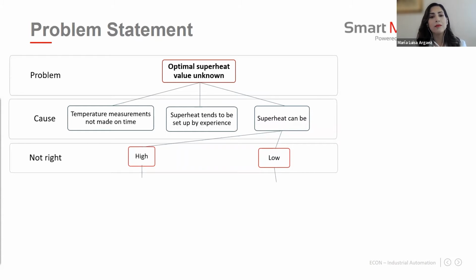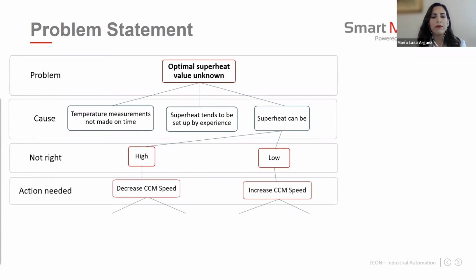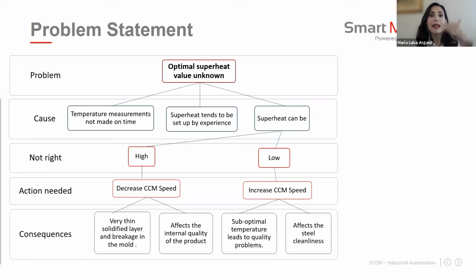Therefore, not knowing the appropriate superheat value to give to the molten steel causes either low or high superheat. So the CCM speed is manipulated to compensate for the superheat variation. And this produces issues regarding quality compliance and operative problems. For instance, when we have a high superheat, it means that the steel temperature is higher than the optimum, and it can be compensated by decreasing the CCM speed, but produces a very thin solidified layer and breakage in the mold in the solidified product.